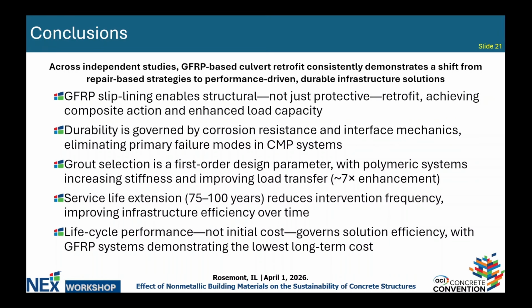The durability is governed by corrosion resistance and interface mechanics. You've seen that the cementitious grout basically completely debonds from that GFRP slip liner, where polymer concrete is able to truly engage that high-strength glass fiber. Grout selection is a first-order design parameter, with polymeric systems increasing stiffness and improving load transfer. You've seen about a 7 times enhancement.